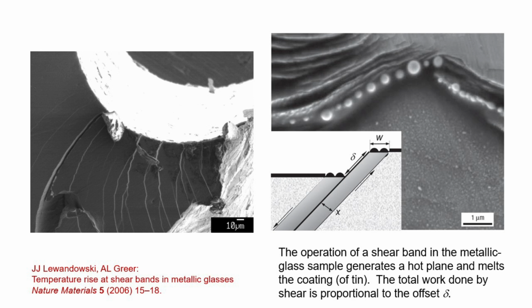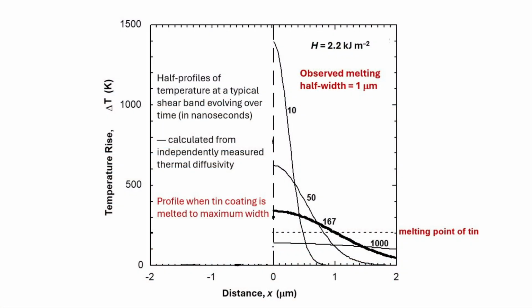And what happens is it does indeed melt around the shear bands in a place like this. You get a distinct zone on this top surface melting, and what we need to do is measure the width over which the melting has occurred. That can be related to a thermal spike, and this heavy line is what we think is the shape of the temperature profile at the point where the melting of the tin has gone to its maximum extent.